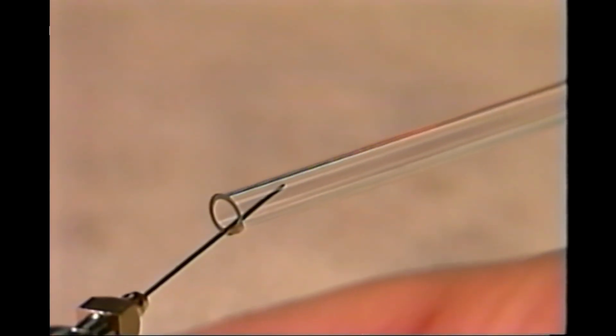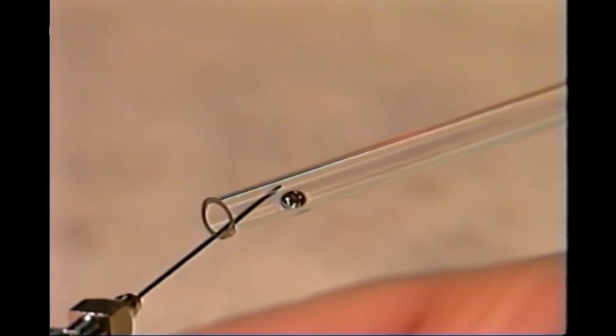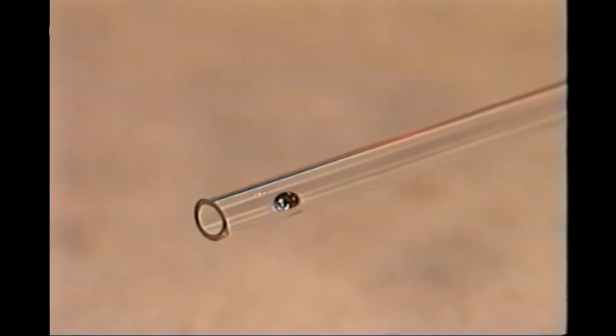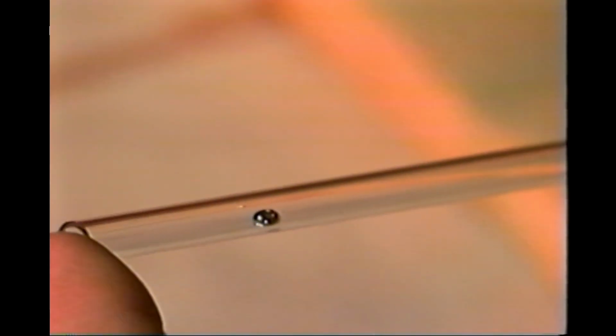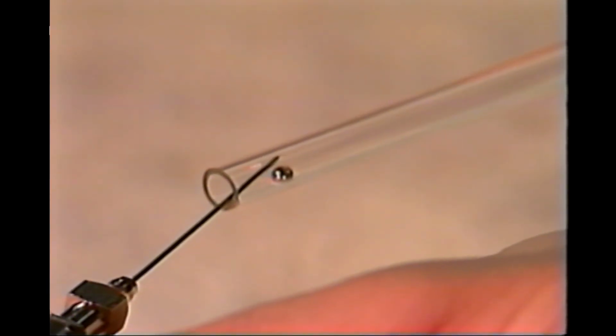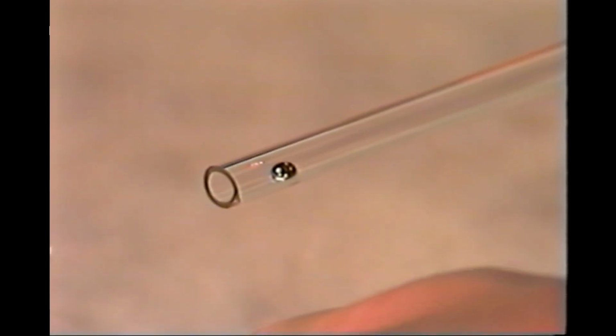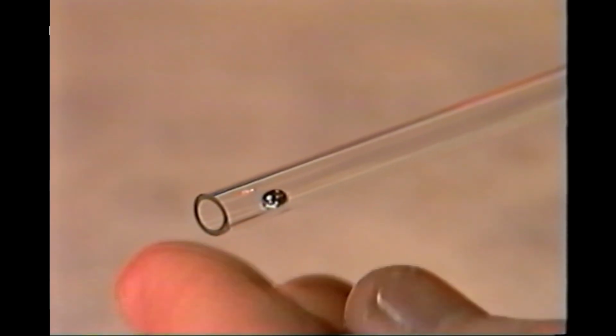Before joining the tubes to the system, the mercury is inserted into a reservoir on the pumping tubulations. Masonlite recommend 400 milligrams or 3 to 4 millimeter diameter ball of mercury for each tube. Excessive mercury can, if being moved around the inside of the tube without care, remove phosphor coating from bends and over a period of time condense heavily on cold areas of the tube, causing severe staining, especially on bends. Too little can lead to mercury starvation, as it migrates from one area of the tube to another and leads to tubes dulling at one end.